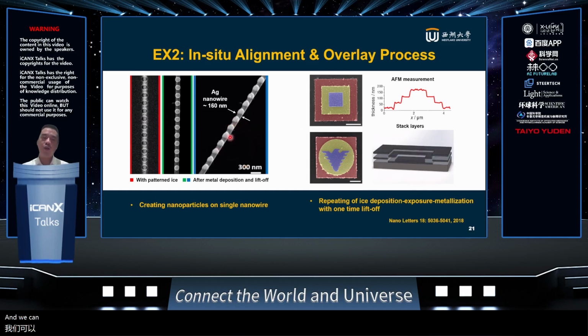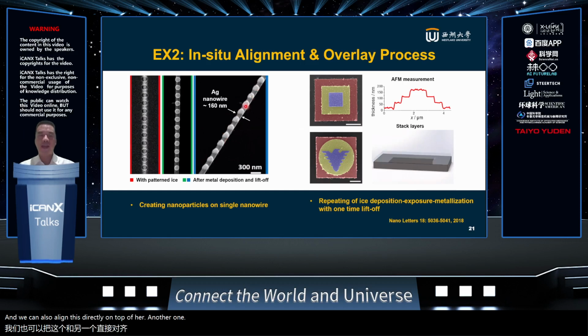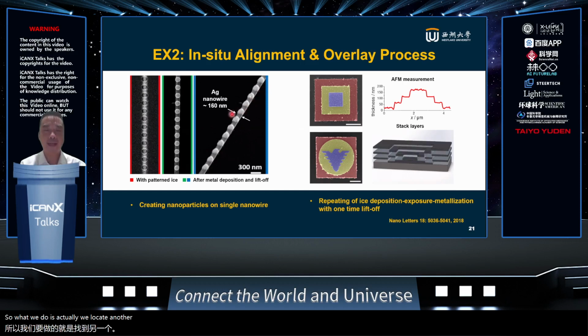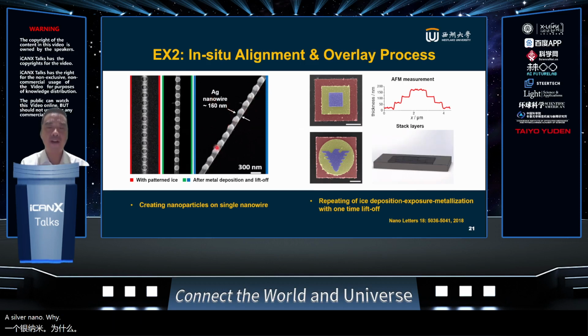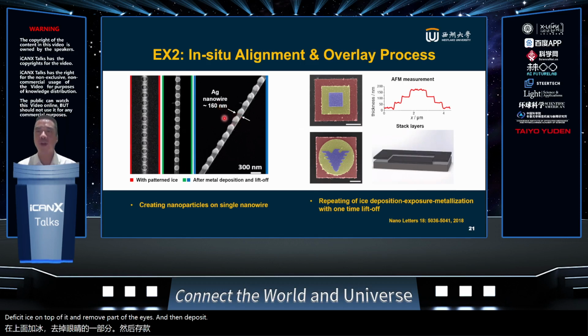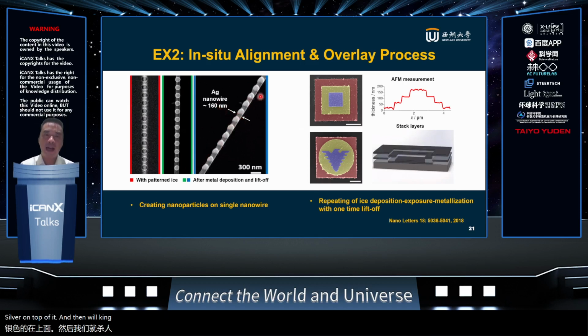And we can also align this directly on top of another one. So what we do is we locate a silver nanowire and find it under e-beam lithography, then we directly deposit ice on top of it and remove part of the ice, and then deposit silver on top of it. Then we can align them properly, in the tens of nanometers resolution, sometimes below 10 nanometers, and align them easily.